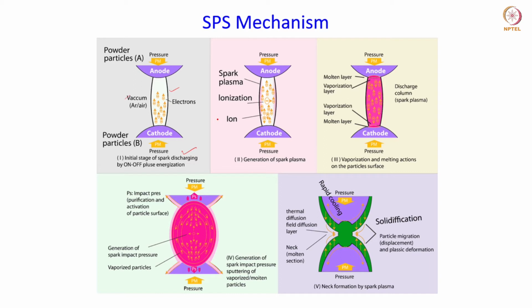And then this electric field leads to generation of the plasma between the particles, leading to ionization, and the effect of this is basically the melting of the particle contacts and vaporization. So this ultimately leads to the cleaning of the surface of the particle and also purification. So vaporization and melting actions of the particle surface are the next step once the spark plasma is generated. Okay. And the impact pressure which is created by the spark also leads to activation of the particle surface, which is again conducive for the bonding between the particles. So the phenomena here are generation of spark impact pressure and sputtering of vaporized and molten particles.